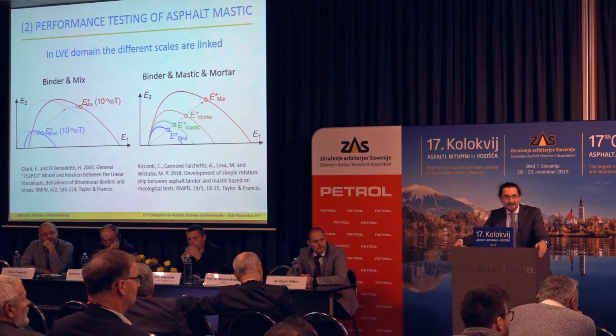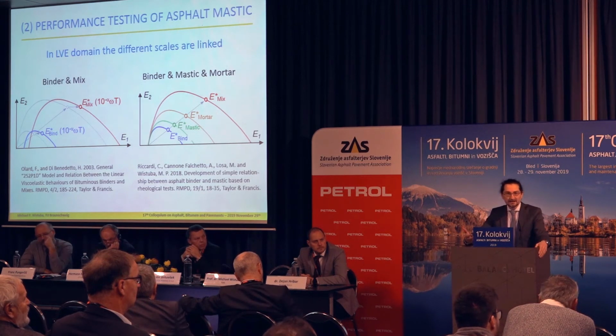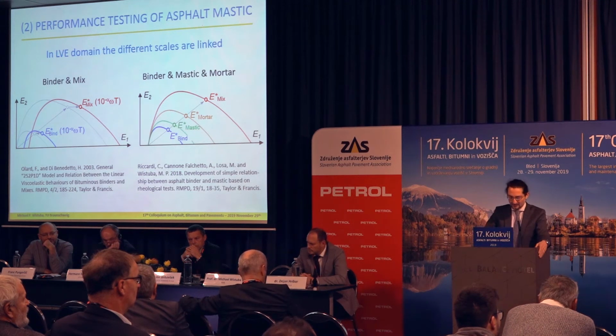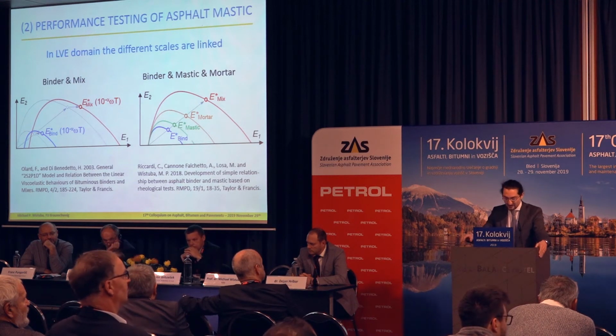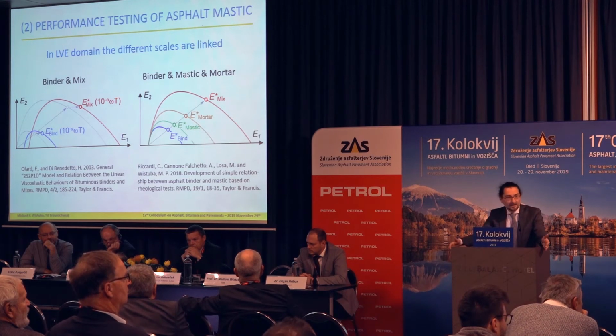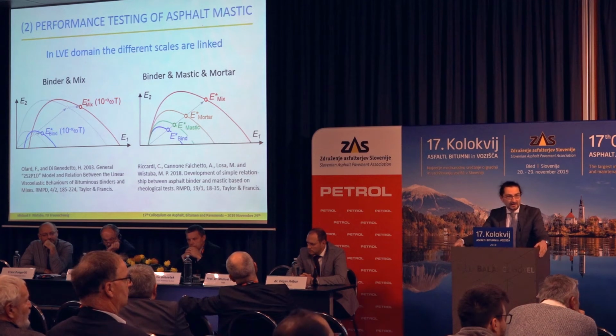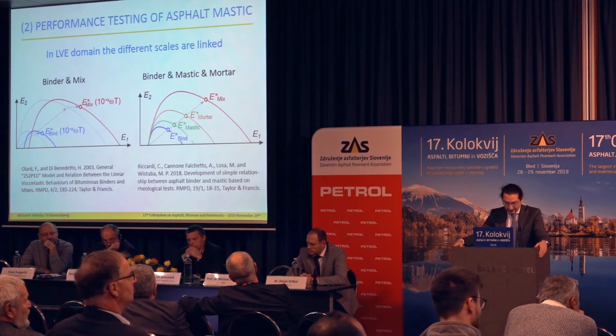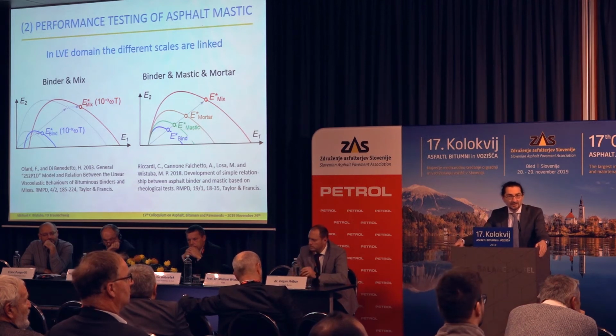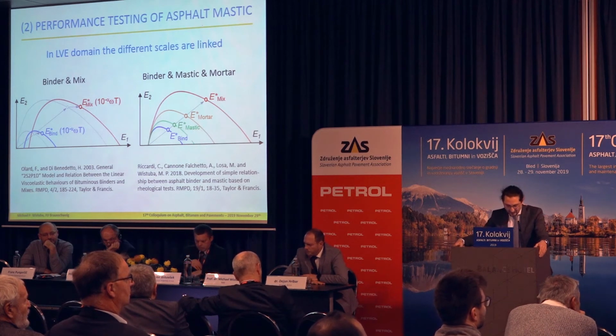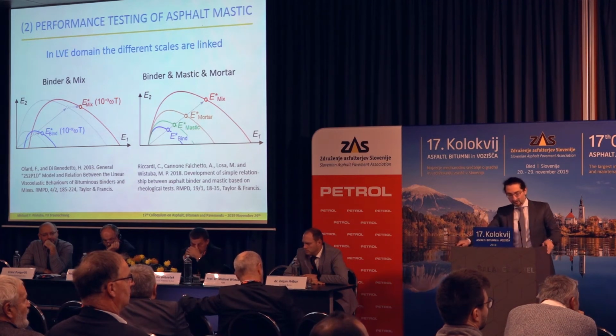So for this linear viscoelastic domain, there is a very clear link of the scales. And so we can predict easily within the linear viscoelastic domain the properties of an asphalt mixture from binder testing. As you see on the figure to the right, there is a link which is shown here as a vector, but this vector has a mathematical background, and you can link all the scales by the 2S2P1D model, which has been presented some years ago by the group of Hervé di Benedetto from University of Lyon. So there is already a link.